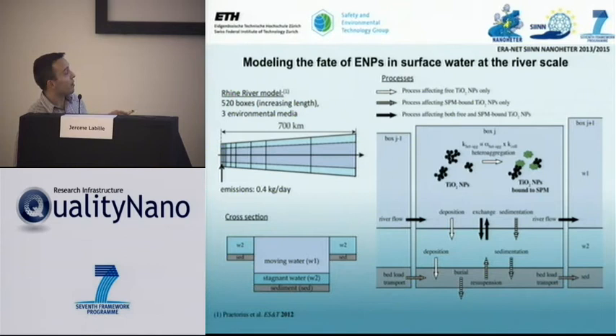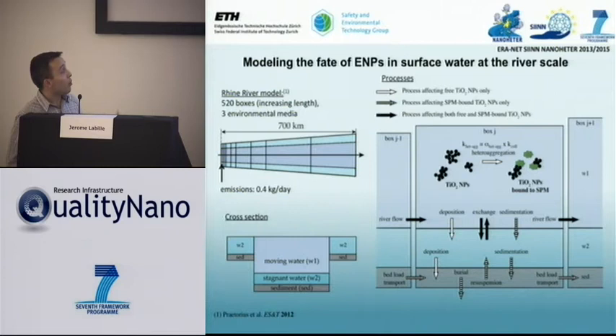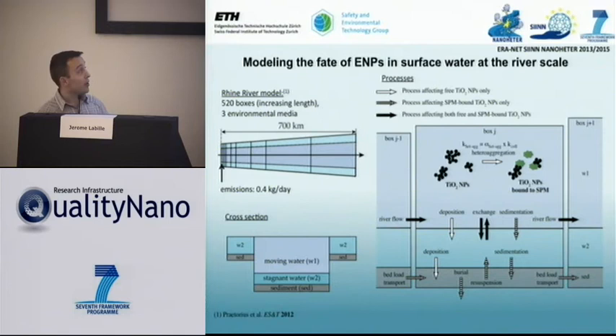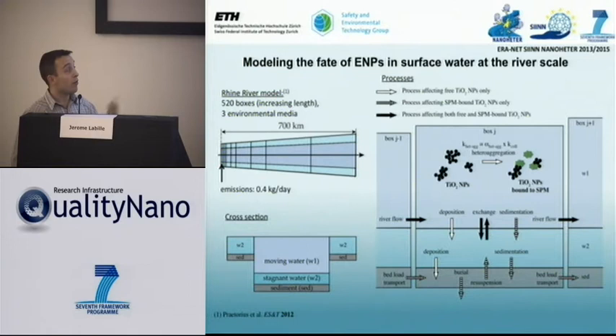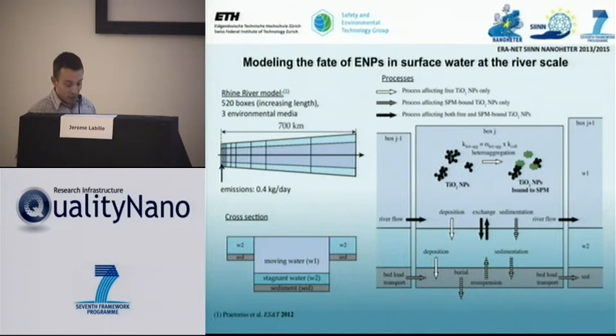Along the vertical axis, you can distinguish moving water, sediment, and the interface between both. The principle of the model is to quantify the amount of nanoparticles in each box along both axes, considering the different mechanisms nanoparticles may undergo: homo-aggregation, when nanoparticles aggregate together; and hetero-aggregation, when they aggregate with natural colloids; as well as sedimentation as a function of aggregate size and hydrodynamic shearing. An unknown parameter to feed such a model is the sticking efficiency between natural colloids and nanoparticles.